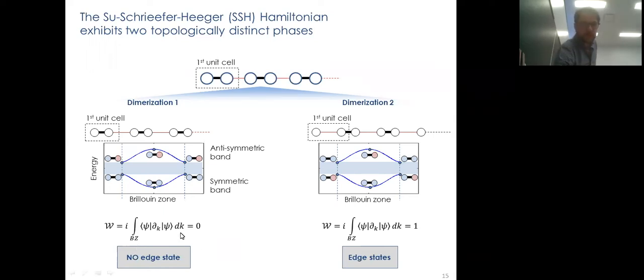And indeed, if we calculate the integral of the Berry curvature over the entire Brillouin zone, we see that in the first case, we have a value of zero, in the other case, we have a value of one. And in the latter case, we are expecting the emergence at the edges of the lattice of edge states. It stays localized at the center of the gap, which is our topologically protected edge state.